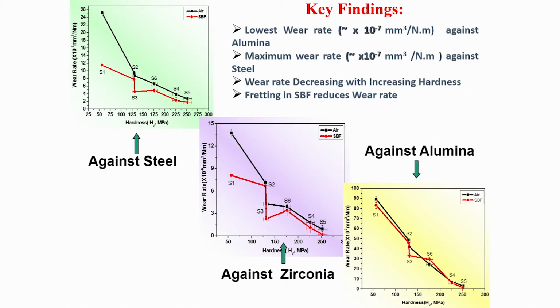So the key findings are that the lowest wear rate is observed in case of alumina, maximum wear rate is against steel, and wear rate decreases with increasing hardness. This points towards the Archard law for abrasive wear: in an abrasive wear dominated situation, typically the wear rate decreases with the hardness of the material.